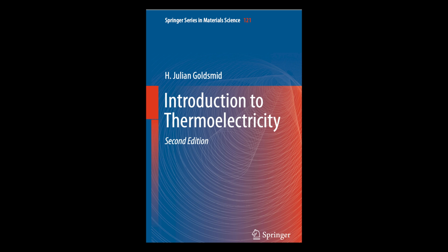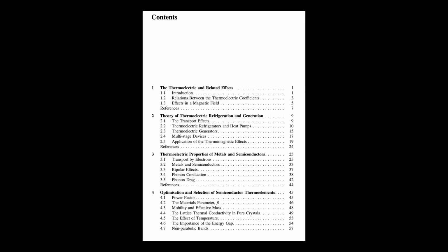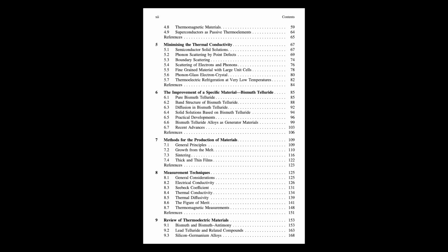Yeah, you can define equivalent parameters for thermionic devices based on work function, barrier height, etc. This lets you define a thermionic figure of merit, ZT, analogous to the thermoelectric ZT. You can compare a thermionic material's parameter with the thermoelectric one. Simple comparison might favor thermoelectrics if electron path length is long, but thermionics might win if their equivalent lattice thermal conductivity is much lower. It's complex.